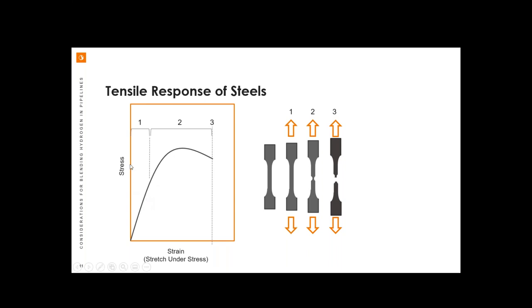And we really have three regions of response to the strain, which is stretch under stress. In region 1, we have this elastic behavior. It's just like a perfect spring. But if we pull hard enough, we eventually get into region 2, where two things are happening. So one, you can see we get this local deformation that's called necking on this coupon or the sample. And in there, and partially throughout the whole sample, we're going to get some cold work, or work hardening. So the steel's actually getting stronger.